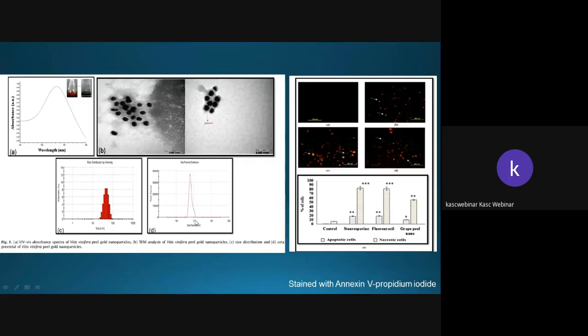The particle size analyzer can calculate the diameter of the gold nanoparticles coated with the phytochemical extracts. The stability of the dispersed gold nanoparticles is decided by the mutual repulsive and attractive forces present between the nanoparticles as they approach one another. Aggregation is avoided with a zeta potential of Vitis vinifera gold nanoparticles found at plus or minus 20 millivolts, confirming that the particles have less tendency to aggregate, exhibiting initial stability of the gold nanoparticles.